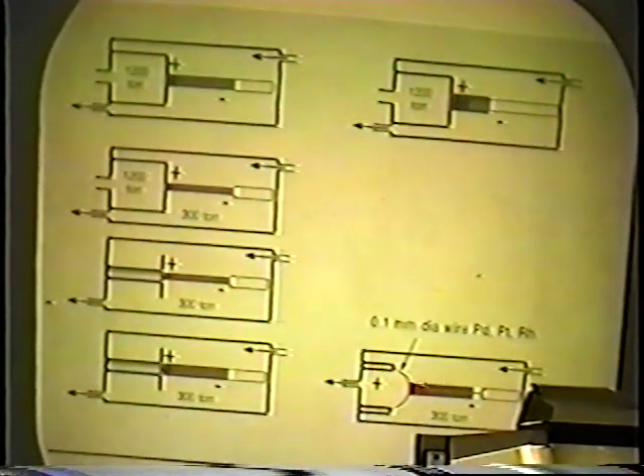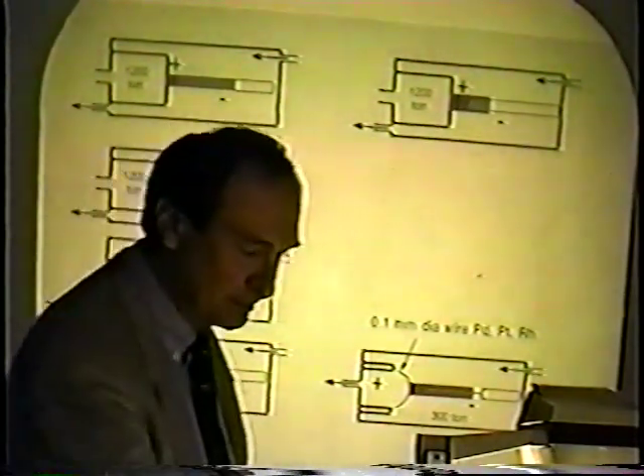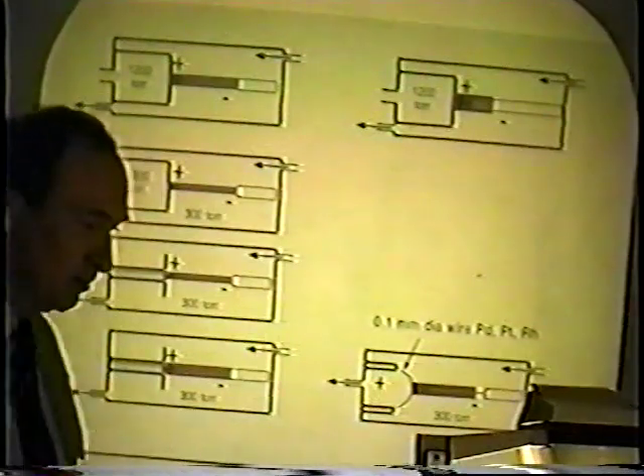These are some of the cell configurations: multiple wire, single wire, plates with high pressure behind them so that we load the plate up. And right now what we're using is this very conservative sort of configuration with a loop of wire. There's only about 30 milligrams of palladium in the system. This has its disadvantage in that when you have a lot of palladium in the system, these plates are like 2 grams, you can watch the loading. But with this small system, because of the volume, you can't really see the loading, so we're kind of flying blind in that regard. And I think we can overcome that to some degree, but right now that's still an open question.